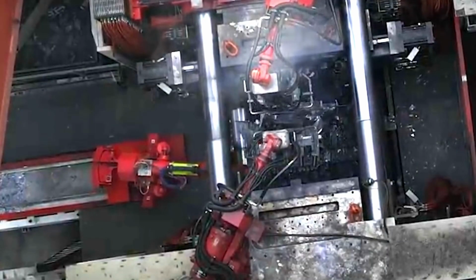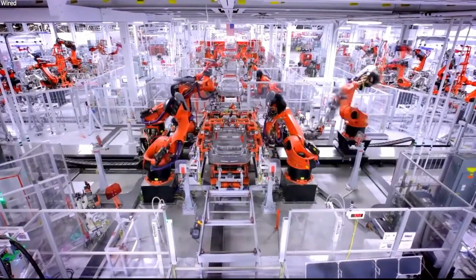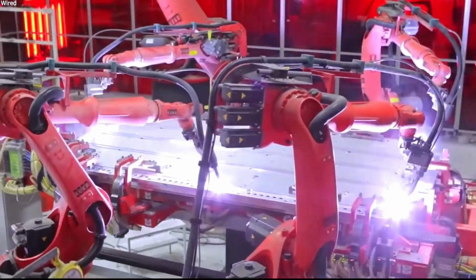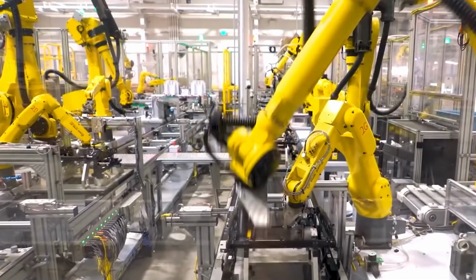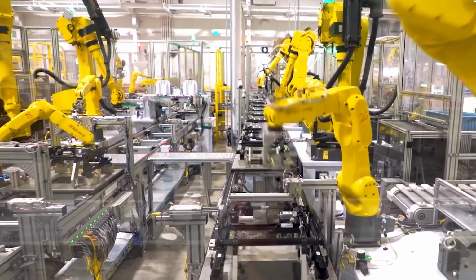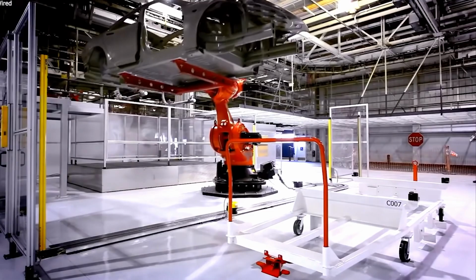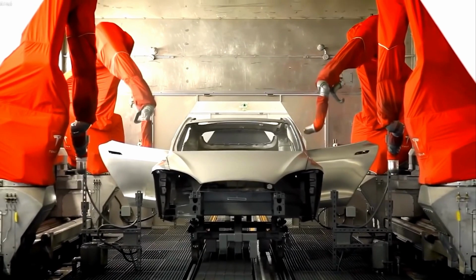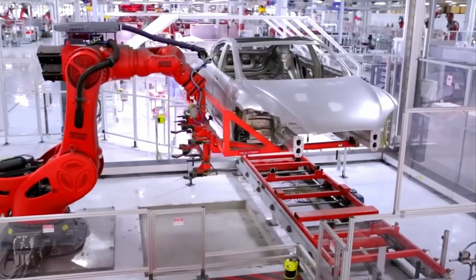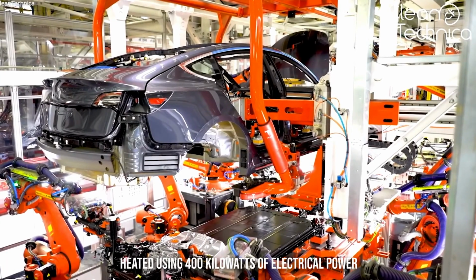For Tesla's Gigapress-based casting operation, ingots and offcuts of aluminum are melted in a natural gas-powered melting oven operating at 850 degrees Celsius until liquid. Slag in the form of aluminum oxide is mechanically removed from the surface. The rest of the liquid metal is pumped through heated pipes to an enclosed warming oven operating at 750 to 850 degrees Celsius, heated using 400 kilowatts of electric power.